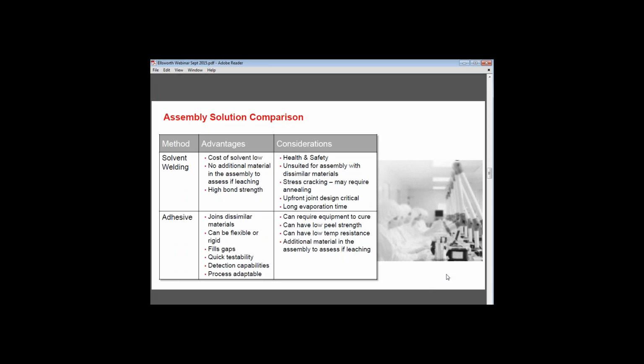And then lastly, for considerations of adhesives, depending on the technology, you could require equipment to cure the adhesive. Again, depending on the technology, you could have low peel strength, and again, depending on the technology, there could be low temperature resistance. Most of those considerations can be managed by the selection of the technology that you go with. And unlike solvents, the adhesive is an additional material that you would have to assess of whether or not there's any leachables.